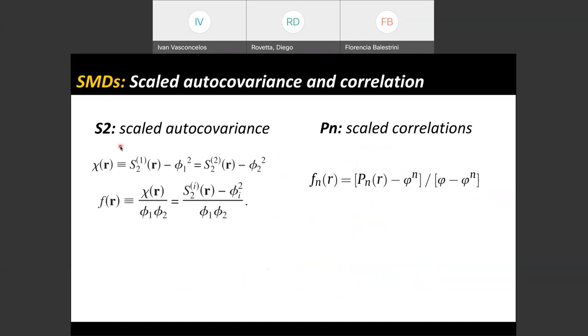in the case of the two-point correlation functions, these are called scaled covariance functions. You can see here how they depend on the two-point correlation function, on the volume fraction, and the relative volume fraction. So you end up with something here that's scaled between 1 and 0. And we can calculate a similar thing for the polytopes.